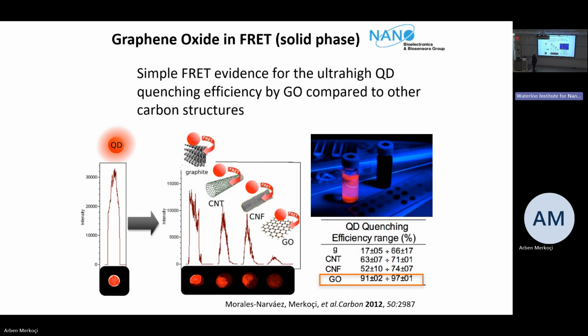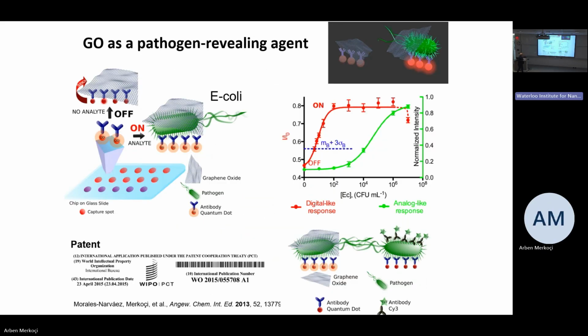So this is a suspension of cadmium selenide, nicely giving some photoluminescence of open excitation. And you see here a total quenching, for example, if we use graphene oxide flakes in comparison to nanofibers, nanotubes, or graphite. So almost 90% quenching capability offered by graphene oxide suspension. With this in mind, we designed a very simple quenching-based operation principle for a biosensor to detect the bacteria.